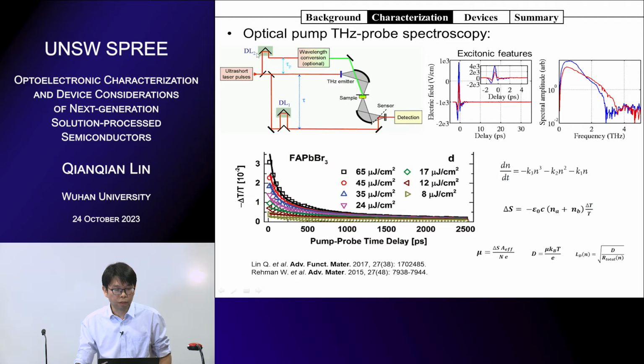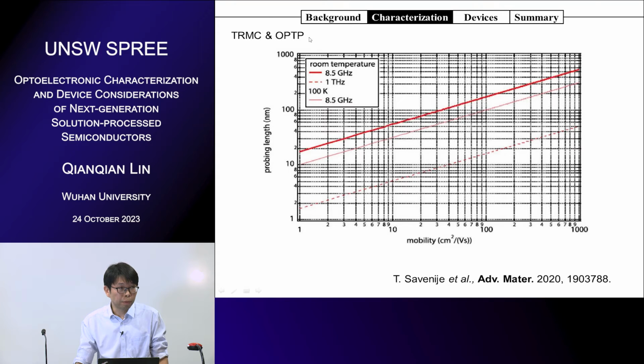So we also use the same thing for the optical-pump terahertz-probe spectroscopy. And from the transients, we also get the recombination constants and the diffusion length, mobility, and so on. And this is a difference between the TRMC and the OPTP. Normally, terahertz has higher energy, and it has a smaller probing length. Normally, it's around a few nanometers or less than 10 nanometers. But for the lower energy microwaves, it has a much longer probing length. If the mobility is high, the probing length could be larger. It could reach around 100 nanometers.